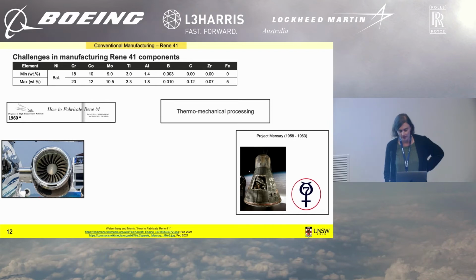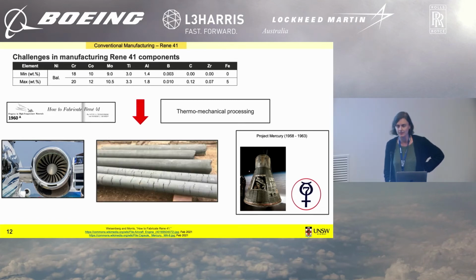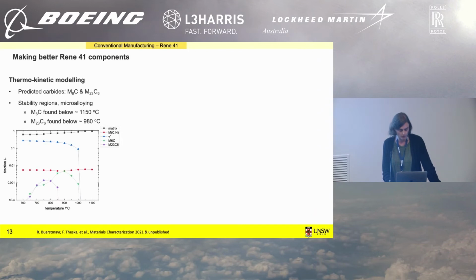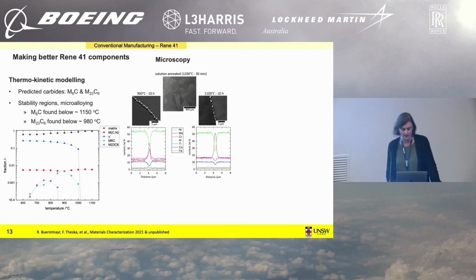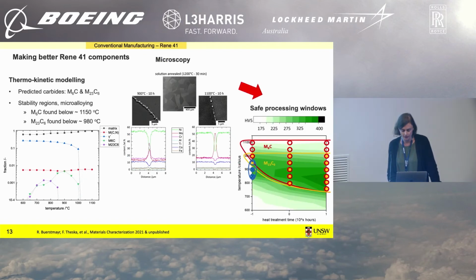aircraft engines. However, it's not easy to manufacture, and if you get it wrong, this happens, and this is going to go back to the scrapyard, and that's going to be huge losses for the industry partners. So what we do in my research is we do modeling, so we can predict precipitation of secondary phases as a function of the alloying contents. We can underpin this by microscopy. And with that, we can define sort of safe processing conditions for my industry partners to make better Rene 41